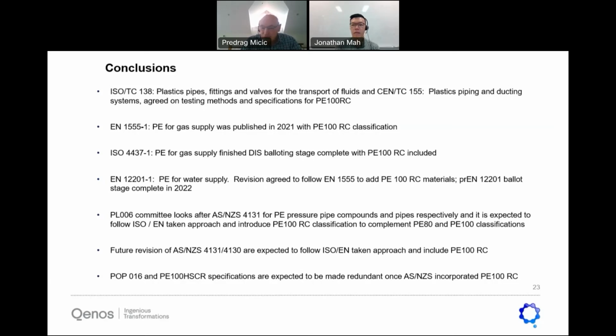But in all these tests that DVGW did, they've done these correlations. So they did benchmarking between the standard notch pipe test, which is done in water, versus the notch pipe test done in an accelerated environment. And they would do all this benchmarking to derive these correlations to come up with a credible number that describes the PE100RC. Let's say 300 hours in accelerated notch pipe test. If you have taken that same pipe and done it in the water, it would last for a year. But that needed to be done across the different labs, etc. So that's why that work took 3 years or longer to establish these correlations, to be able to trust the data.